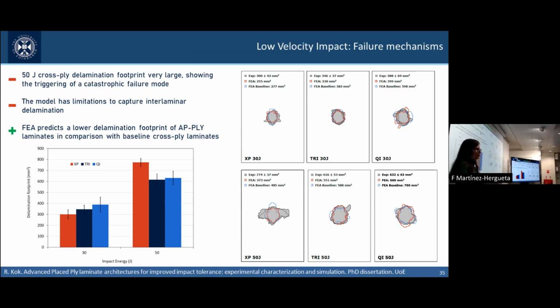Delamination is driven by shear in-plane stresses, and those shear in-plane stresses for the AP-PLY laminate are mainly originated in the undulations. As you know, a strain gradient to be well represented needs lots of elements. And instead of using lots of elements, we are using just 4. That means that we can predict there is a gradient. We will see a difference in strain, but we cannot predict the magnitude. We are limited on that. Our model is very much optimized to capture fiber failure rather than delamination.